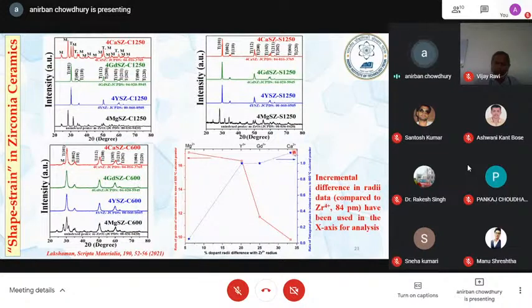Now, if you see the calcia doped zirconia ceramics previously, people were doing it at 8% and 16%. We are just doing it at 3 or 4%. So less than half or one fourth of their amount we are using, and we are making this tetragonal phase stabilized. Tetragonal phase, as I said, is important for dental applications, mechanical properties, thermal barrier coating, and many others.